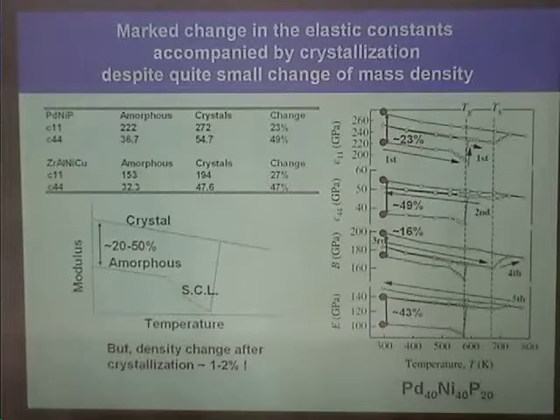So you mean the liquid transformation. Well, you're implying that this is unusual, that the change in elastic properties of 20-30% is really, really big for a density change of only 1 to 2%. But I'm asking whether maybe that's typical. That's right. If you take a crystalline metal and melt it, you change the density by only about 4%, not a whole lot more than that, and you change the elastic properties from 10 to zero because it becomes a liquid. It has no shear modulus. So maybe this is not unusual.